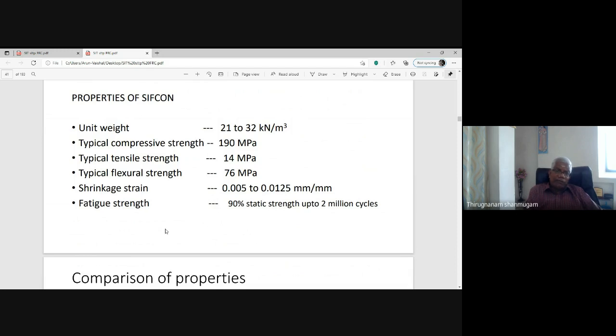The typical properties of SIFCON, as per the literature: the unit weight of SIFCON is similar to the unit weight of concrete, but there is a slight variation depending upon the volume fraction of the fibers. If the volume fraction of the fiber is about 4%, it is 21 kilonewton per meter cube, because it will not contain the coarse aggregate, so it's a slight decrease in unit weight. But if the volume fraction of the fiber is 10, 12 or 14%, then it produces higher density, about 32 kilonewton per meter cube, because steel has higher unit weight. So the unit weight of concrete is approximately 25 kilonewton per meter cube, similar to that of RCC.